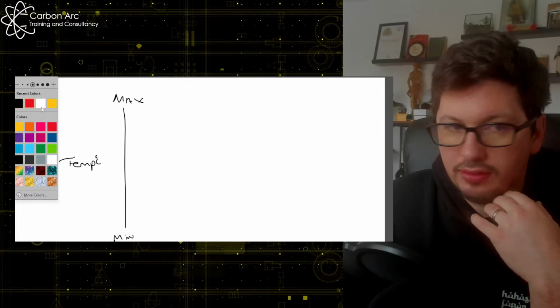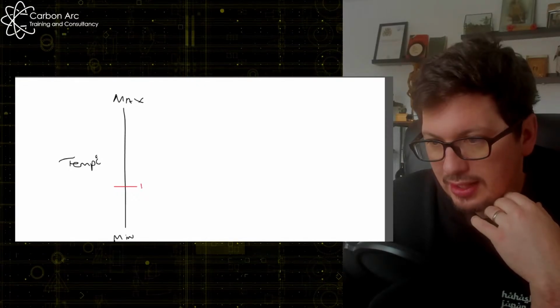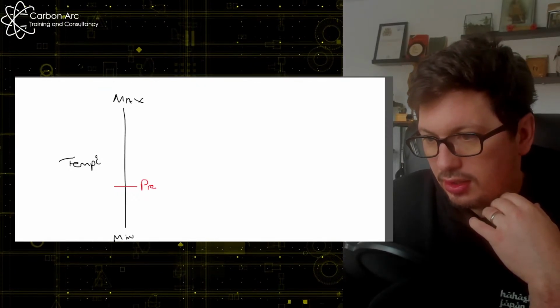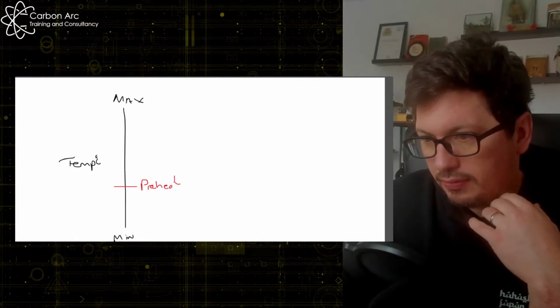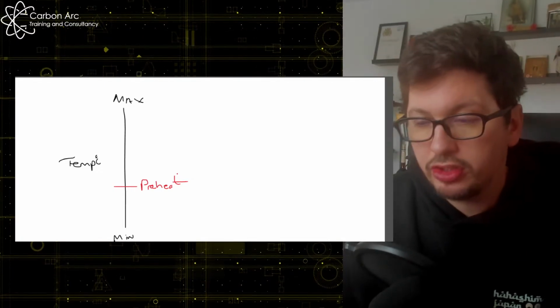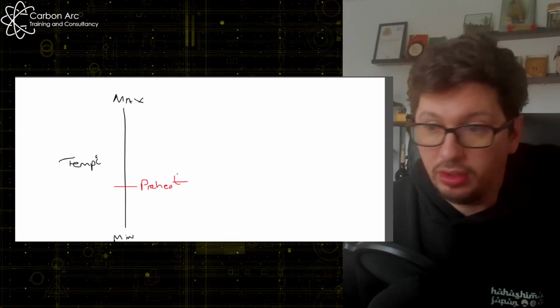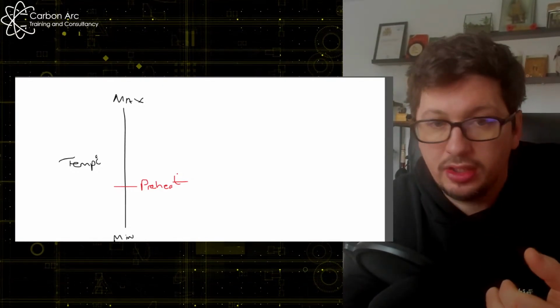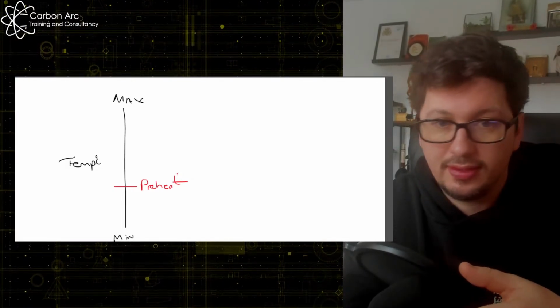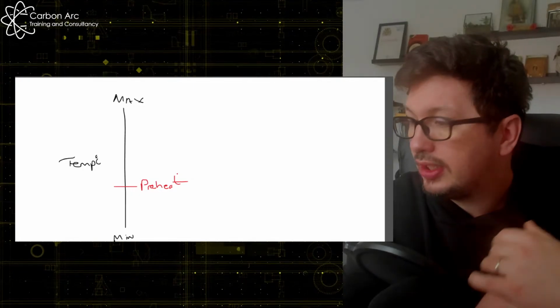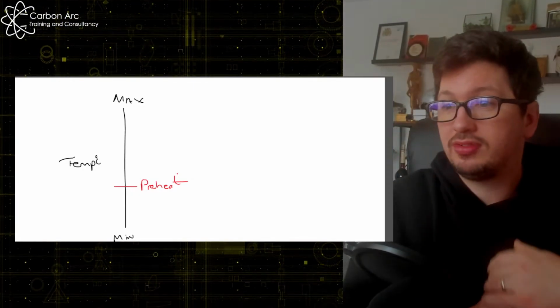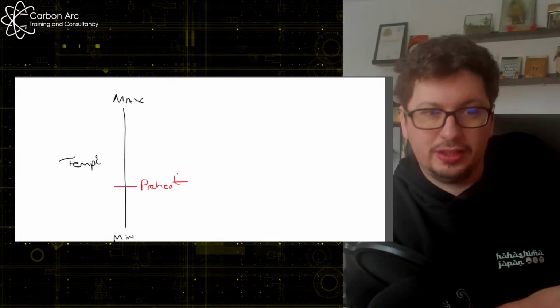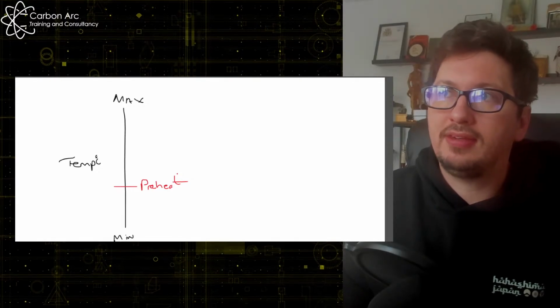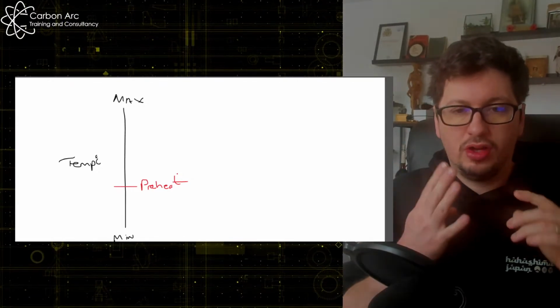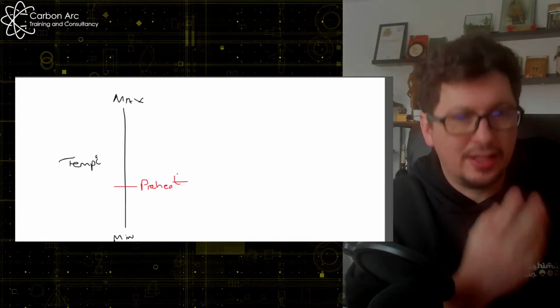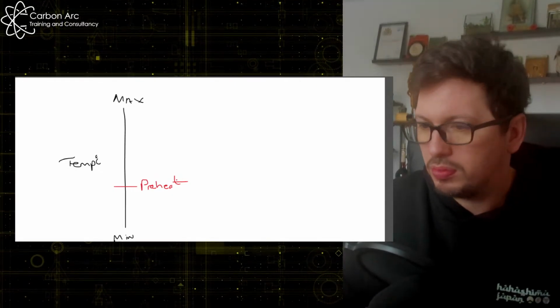So what I'm going to do is put a line on here and say, right, this here is my preheat. So I've got a preheat temperature here. Preheat temperatures change depending on what we're doing. It's the material, so the CEV of the material, the thickness, all sorts of things. Each standard looks at it slightly differently. Some standards, like AWS D1.1, just say if it's this material thickness, here is your preheat value. BS EN 1011 gives you questions on combined material thickness, CEV, etc. Heat input is one of them as well.